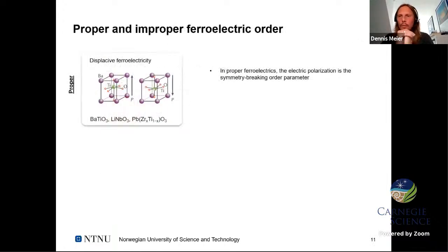Okay, so let's start with something that most of us will know. If I talk about a proper ferroelectric material, what I have in mind is usually a displacive ferroelectric like barium titanate, lithium niobate, or PZT. These are the textbook ferroelectric materials where I would say they are proper ferroelectrics. The ferroelectricity or spontaneous polarization in this case originates from an off-centering of one ion. In this illustration here, the titanium ion moves upwards. And because of that, the material develops a spontaneous polarization pointing upwards in the left-hand scenario and pointing downwards in the right-hand crystal structure. So here, the electric polarization is really the symmetry breaking order parameter driving the transition from the paraelectric to the ferroelectric state.